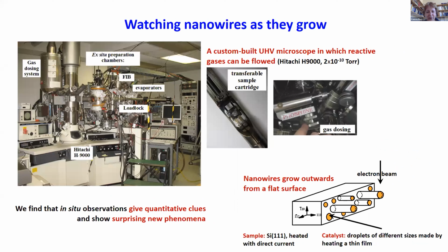So let's consider a bit how it is that we're going to study this process and what we can hope to learn about it. So here's a photo of the microscope at IBM. Here's the microscope itself. It's been modified so that we can do these chemical vapor deposition processes in real time in the microscope. So you need an ultra high vacuum within the microscope that's achieved by some extra pumping. You need a delivery source for the gases, including some toxic nasty gases that you want to be really careful about handling. You need a sample insertion that can be compatible with UHV. So we have a disconnected sample cartridge that gets fed into the microscope and then can move to other locations within the vacuum system where we can clean it, calibrate the temperature, deposit material on it, etc.